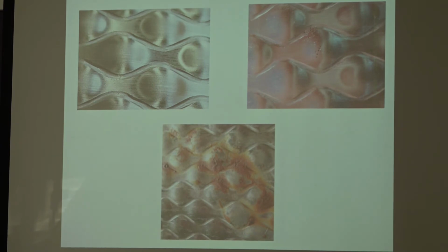You can see three conditions here. The top left is the original surface. The bottom is what happened and why the owners complain. No, it's the repair. This one is the repair. And the upper right is a corroded one. The order is not perfect here. So it's a corroded one, and you can see the small pit. You see the little black spot? This is where the rust was starting from.